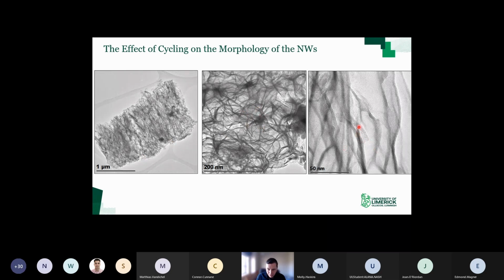And zoom in even further, you can see approximately 5 nanometer diameter consistently for all the ligaments, which told us that this is actually the stable morphology that you need. So this 5 nanometers is the stable morphology. It's not the nanowire initially, it's this structure that is the stable structure. Even if you took the material after 1,000 cycles, you would still see this dimension as well, so it doesn't deform any further.